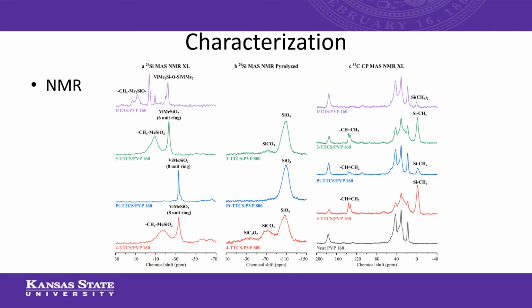NMR was performed also to determine the cross-linking behavior and then the overall final composition. From the most left graph, you can see that the 4 TTCS, 3 TTCS, and DTDS, after the cross-linking, they all form a rigid structure. But the platinum TTCS did not show a very strong rigid structure after the cross-linking. And then also in the pyrolyzed signals, platinum TTCS shows mostly, I say, all four structures, which means very less silicon to carbon bonding in the platinum TTCS. This result corresponds to the previous XPS result.